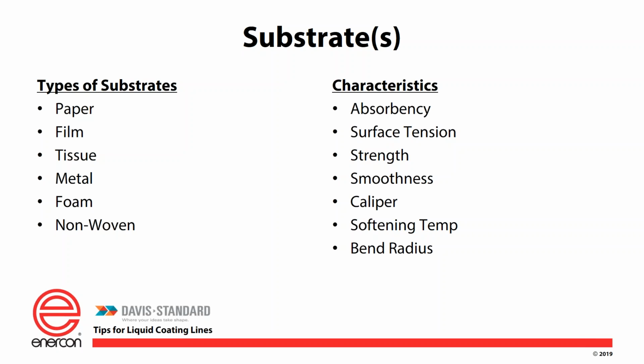Caliper, that's the thickness of the webs, right? The thickness of the web has a lot to do with setting up the coater as far as gap controls, but it also matters on your idler rolls to transport a web. If you're going to run, let's say, a triple up foil, we've got to handle that at the speeds without creasing it. A paper can run a smaller diameter idler because we can pull a lot of tension across those idlers, whereas a triple up foil needs a little air boundary to float. So we use a larger diameter to create a hydraulic force of air underneath it. Whereas board, heavy duty cup stock boards and stuff, you need larger diameters because of creasing and bending and cracking of the board. So you've got to have large radius turns. You can't use the small diameter idlers. So we're looking at calipers for multiple reasons of the substrates.